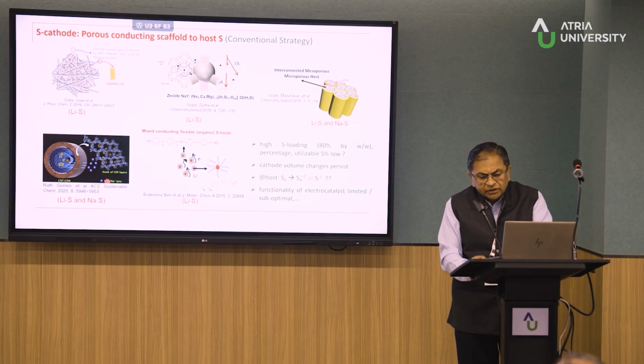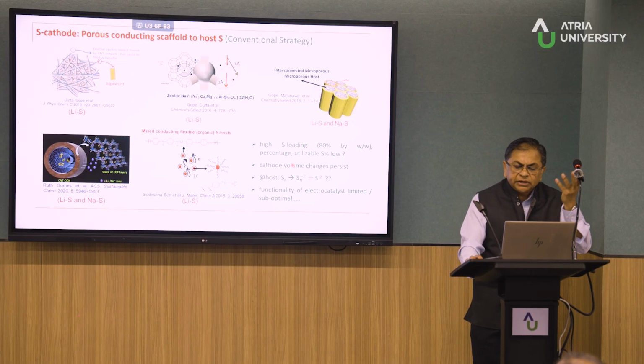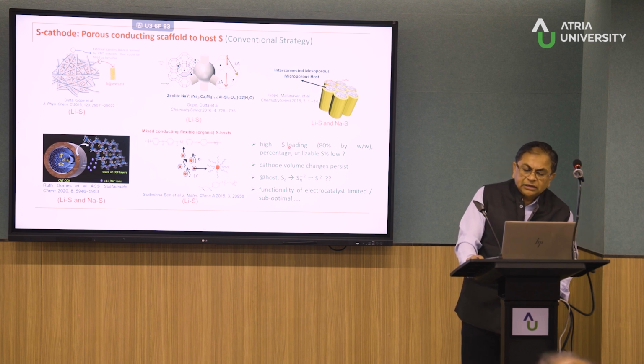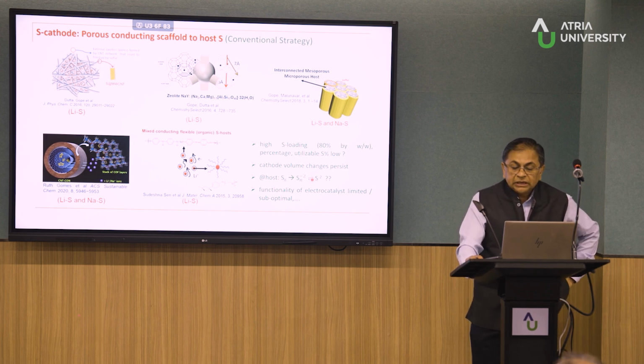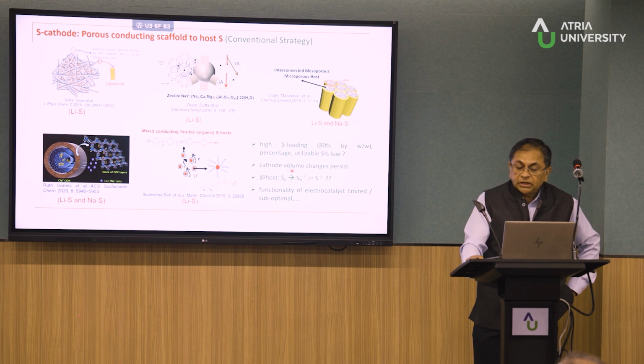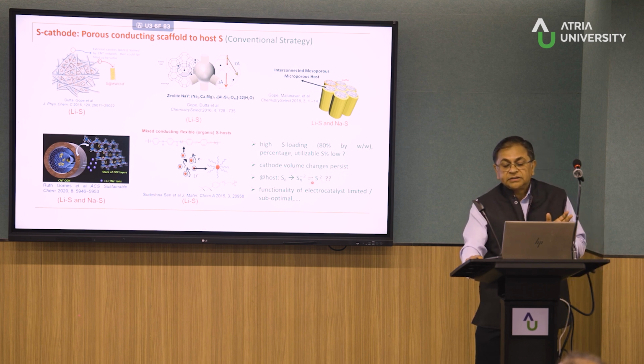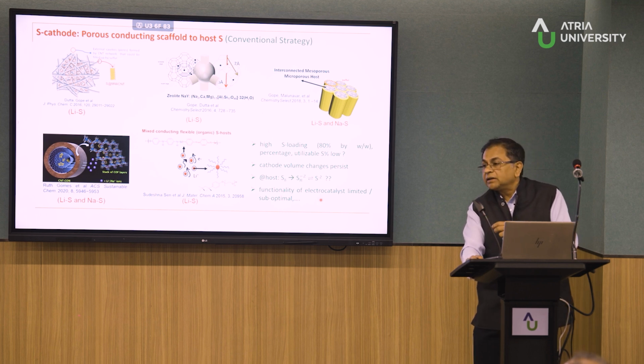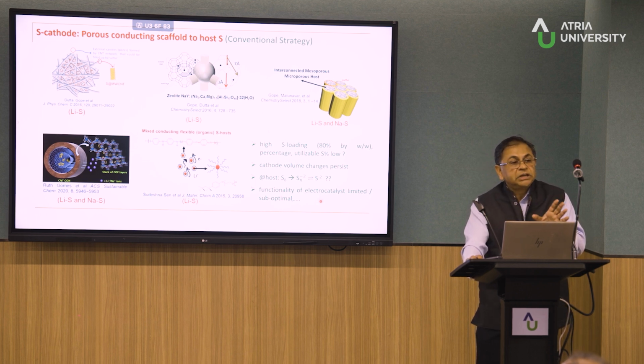Okay, so the motto of this is, of course, you can design good hosts, you can publish well, but the cathode volume expansion still remains, and we have completely no clue on the mechanism of the trapping in these systems, right? And even if, in this very high porosity host, you want to introduce an electrocatalyst, the role of the electrocatalyst is completely unknown.